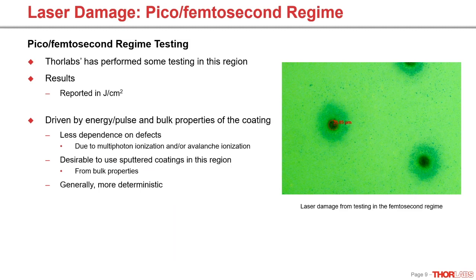Next, we have the pico and femtosecond regime. And you can see here that these are some very tightly and finely drilled holes. Basically, with shorter pulse widths, you tend to be able to get cleaner ablation and better drilling. And that's because at shorter pulse lengths, there's less time to diffuse heat into the substrate. So you're just getting pure ablation. There's less melting, which is why pico and femtosecond lasers are often used for material processing. Anyway, we have done some small amount of testing in this region, again, at customer demand. And these results, like the nanosecond regime, are reported in joules per centimeter squared.